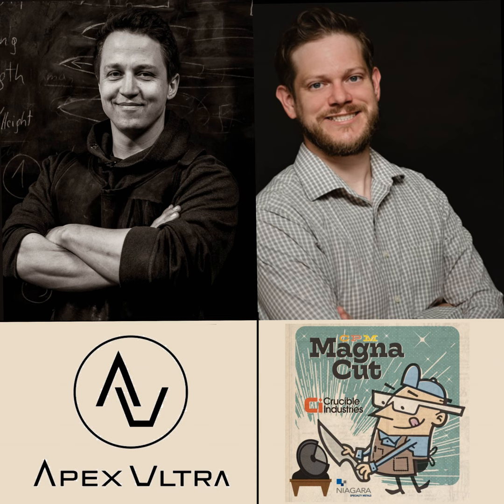So you have less oxidation in the first step, and then you go directly into hot rolling, and you don't do the electro slag remelting. So the question is how similar or how good of a product will it be at the end? And the answer to that weighs 7 tons and is a huge experiment that is slightly expensive. But that's the smallest VIM, so vacuum induction melting furnace that we have in Central Europe.